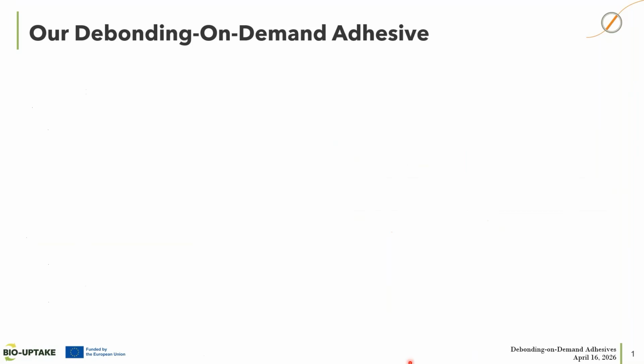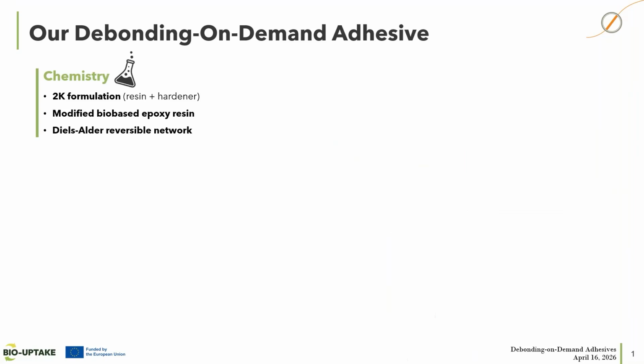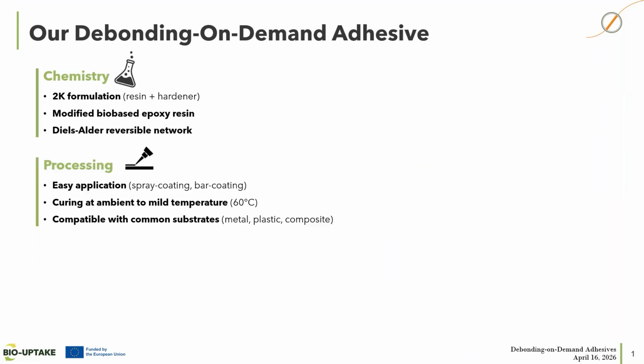So now let's have a look at our actual adhesive formulation. So it's a two-component system based on a modified bio-based epoxy resin, which is combined with a reversible Diels-Alder network. And the key advantage of this solution is the ease of use, because it allows the use of standard application methods such as spray coating or bar coating. Also, curing is made at ambient to mild temperatures up to 60 degrees. And this solution is compatible with common substrates such as metal, plastic, or composites.